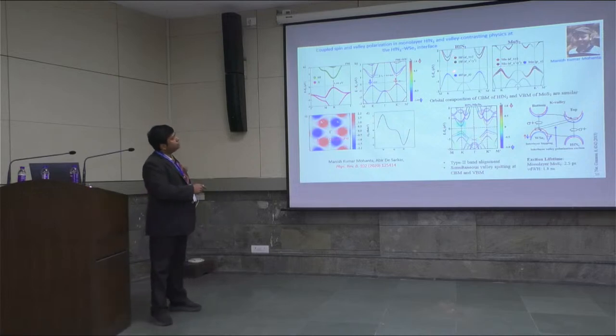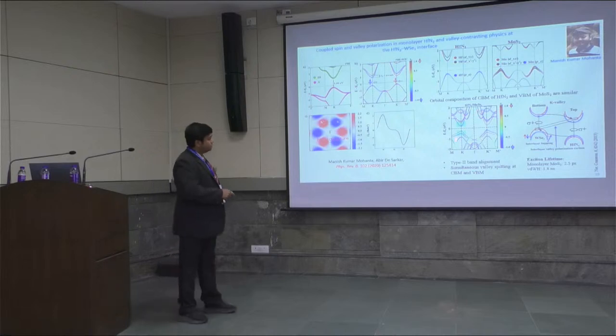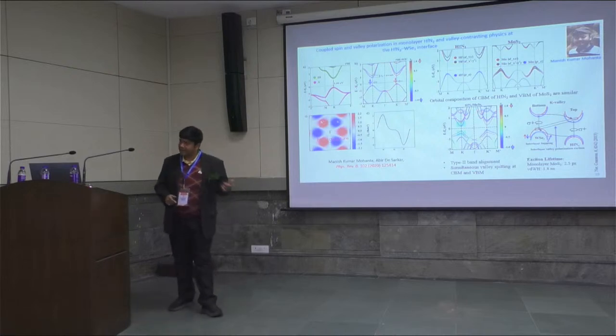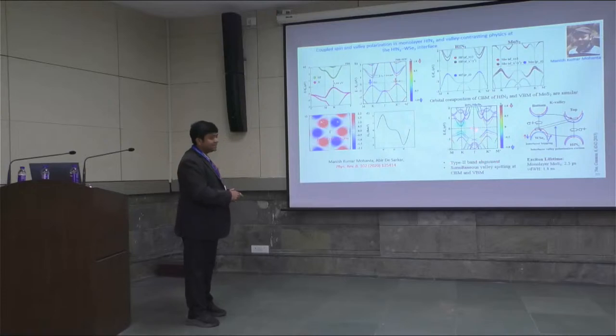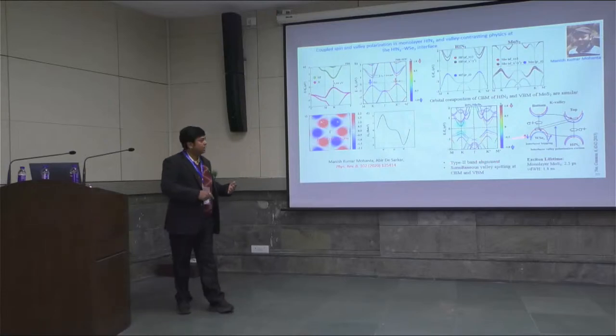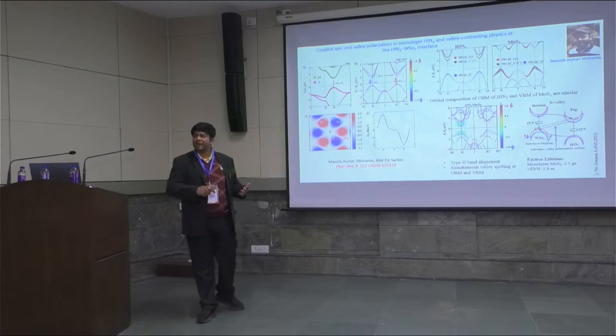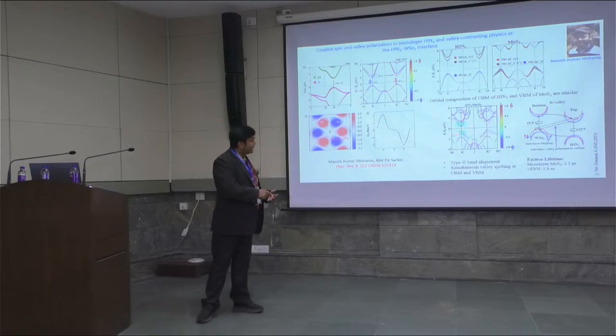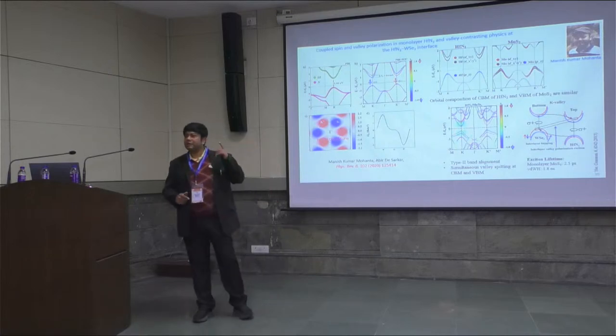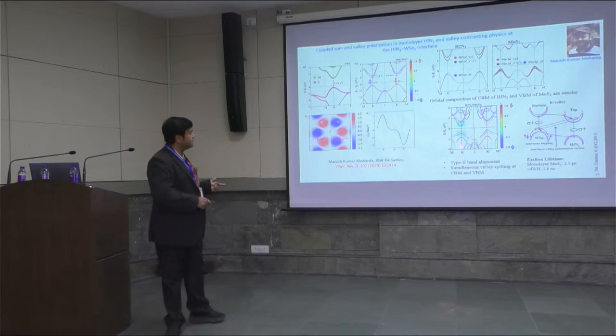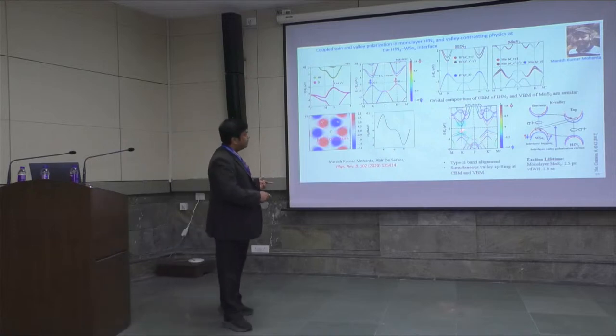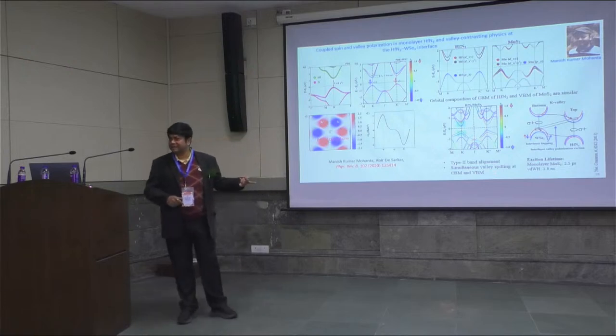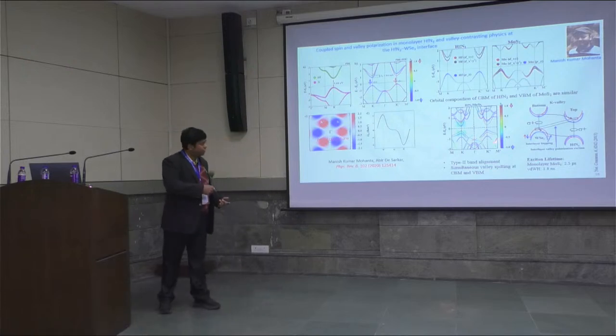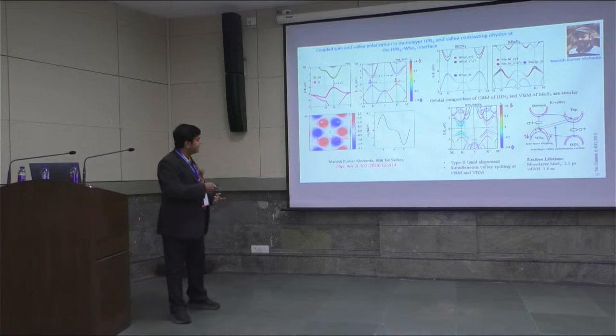So when the HfN2 monolayer is stacked on top of molybdenum telluride, to form a van der Waals hetero bilayer, a type 2 band alignment arises in it. As a result, we are able to realize a large Zeeman type valley spin splitting at both the conduction band and the valence band. So this will be ideally suitable for valleytronics applications, because in a van der Waals hetero bilayer, one can prolong the lifetime of valley polarized excitons. So I'll talk about the type 2 band alignment in the next few slides.